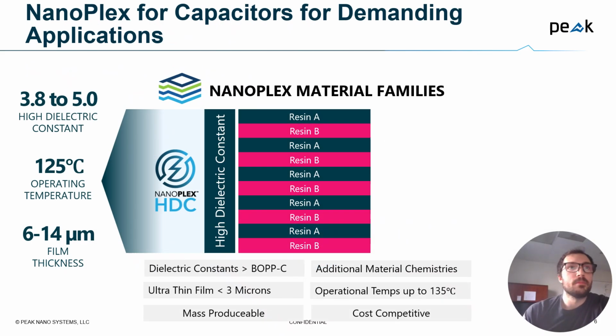And so one example of this, in a more practical sense, is that we can take two resins and make a film with extremely high dielectric constants, up to about 5. These have extremely limited leakage currents, and so this really enables extremely high energy densities relative to if you were just to take a single resin, make it bulk, and the properties you might find with something like polypropylene, which is the current standard, and we'll talk a little bit more about that.